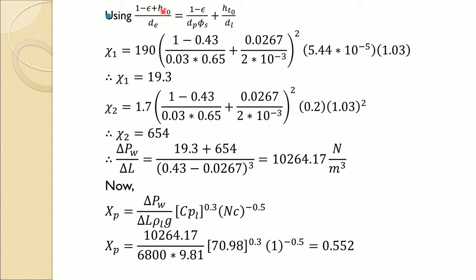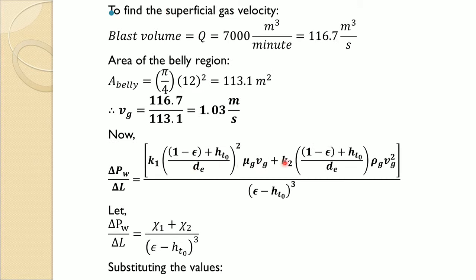So, in dE, what we have done here, again, we have assumed the total hold up which was there in the equation in presence of gas. We have substituted that total hold up with the hold up in absence of gas, h t naught. This is given and quite reasonable, that for the pressure drop equation in liquid or metal flow we can use this for simplification.